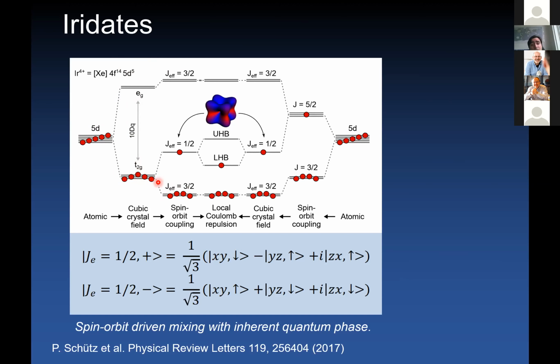Now, if you consider spin-orbit coupling in this context, you realize that spin-orbit coupling is so strong that it leaves the orbital angular momentum partially unquenched. So effectively in this system, the orbital angular momentum can be described as an effective orbital angular momentum 1, which summing up with the spin 1/2 of the electron forms the J effective 1/2 state and 3/2 states. So the 3/2 states are lower energy, and the J effective 1/2 state is at higher energy, where the chemical potential lies. So this band can be fairly narrow in certain systems, and therefore you can have a Mott instability.